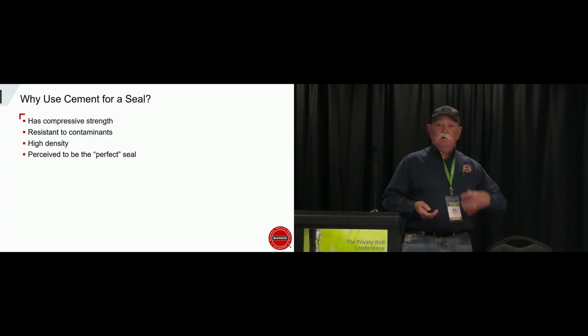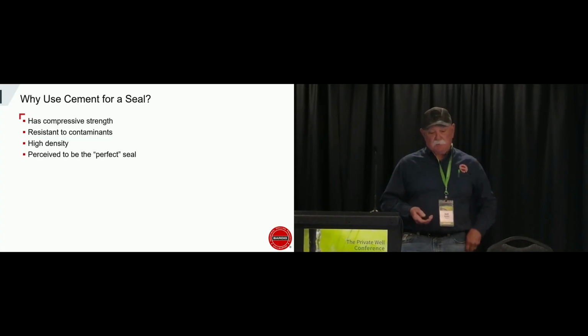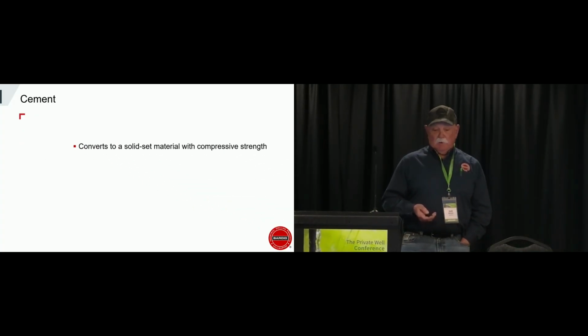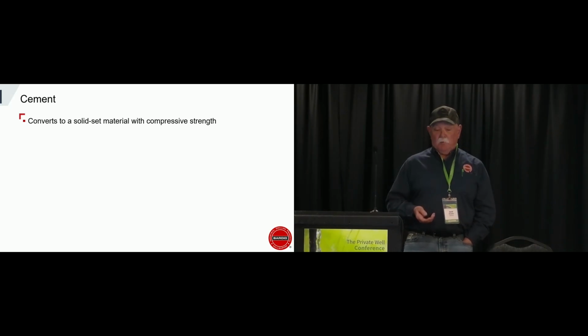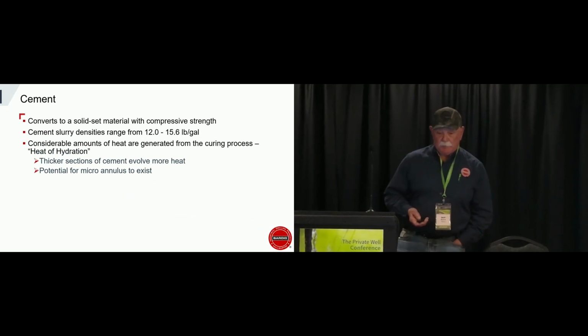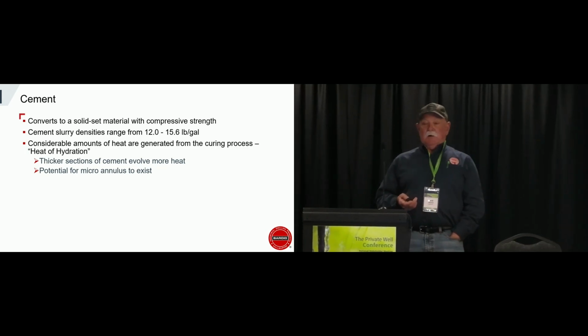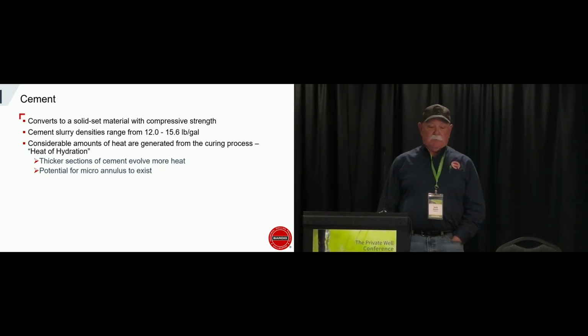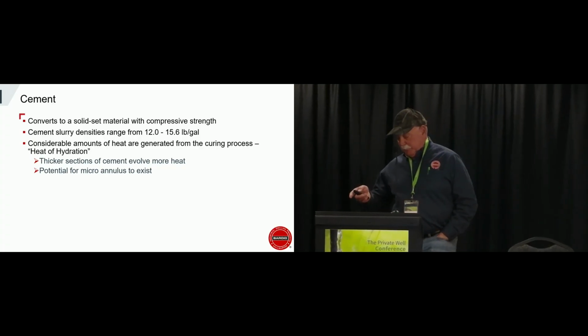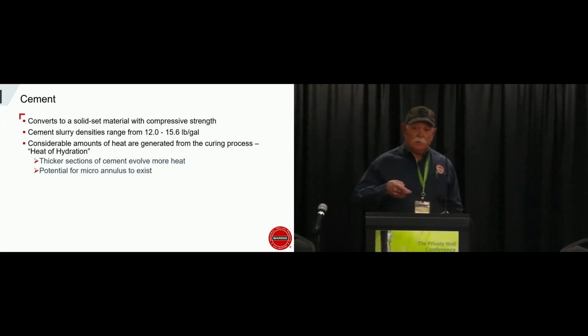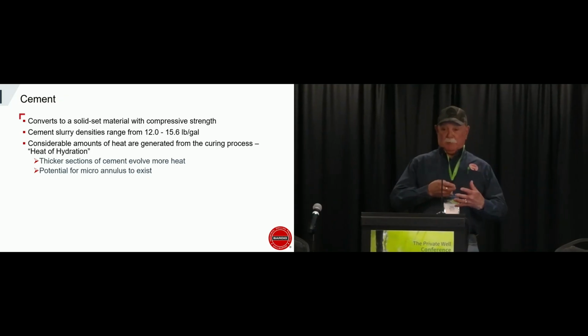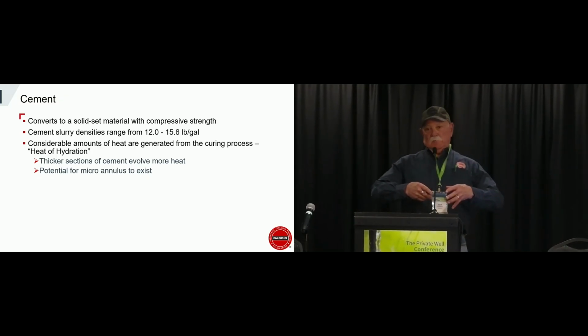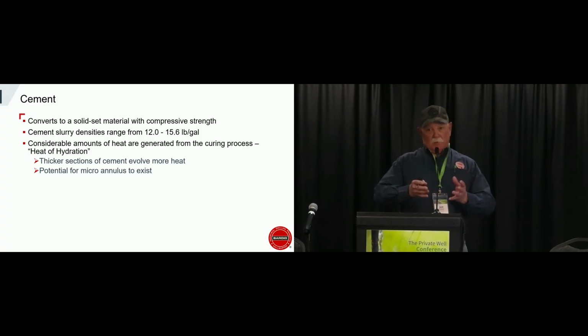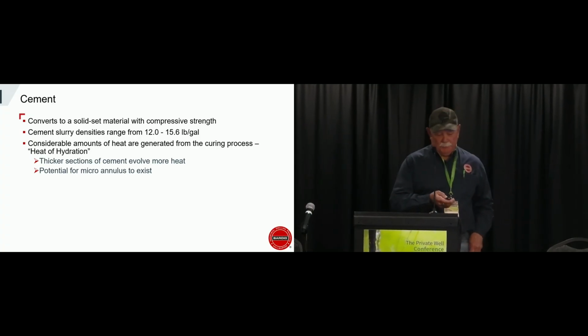They're high density, so if you have artesian conditions, a lot of people used to say cement's number one. So it becomes a strong material, 12 pounds per gallon up to 15 and a half. The thing about cement, heat of hydration, it can collapse PVC. You create a microannulus in steel pipe, where it expands, and when it cools, it contracts, and now you have a microannulus.